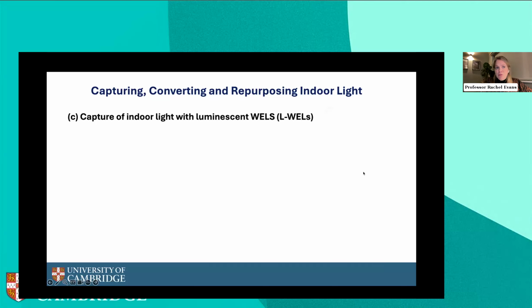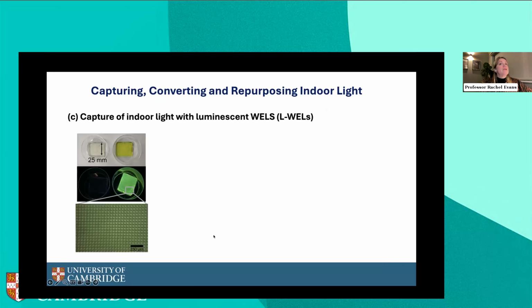So the next step is to integrate the fluorophore with the well to make a luminescent waveguide encoded lattice, or L-well. And we just do this by adding the fluorophore to the photopolymer solution before we encode the waveguide. And so you can see our bulk well here under UV light, and it gives out this green fluorescence. And when we zoom in, we can see, in fact, that there are these encoded waveguides within the polymer film.